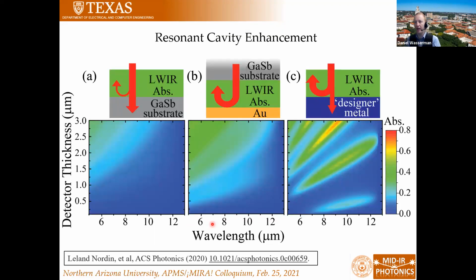So how can we integrate our materials into detector devices? Well, the simplest way we could do it is, again, make a cavity-based device. What I'm showing here are simulations. This is the absorption for a long wave IR detector as a function of thickness and wavelength, just grown on an undoped substrate. You can see that absorption is very weak. It's in the 10% range, even once you get up to 3 micron thick detectors. Now, if you were to put a metal film at the bottom of your detector, you would get essentially a double pass geometry, and you would be able to bump this up to maybe 20% or so.